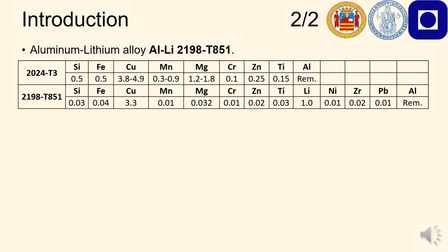The alloy under analysis is a third generation aluminum lithium alloy 2198 in the T851 temper. The metal was solution heat treated, stress relieved and artificially aged. The typical chemical composition of this alloy is listed in this table, compared with the composition of the 2024-T3. It is worth noting that the 2198 presents 1% of lithium that allows to achieve a 3% of weight reduction if compared to the traditional aluminum alloys.